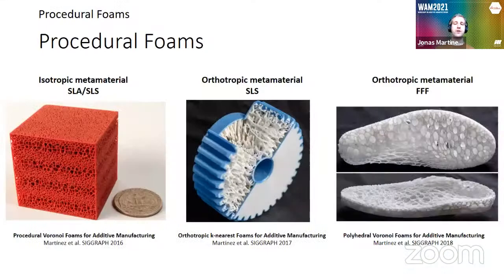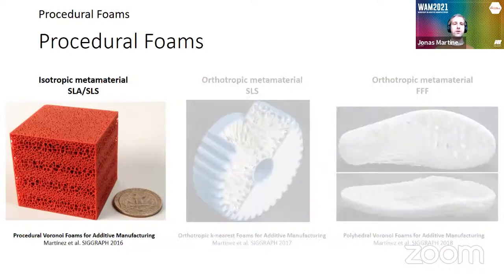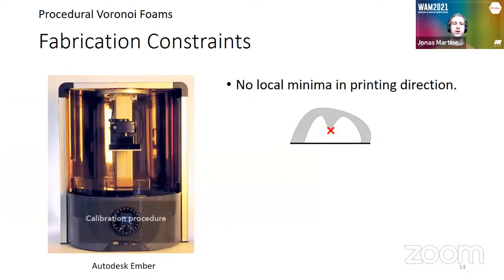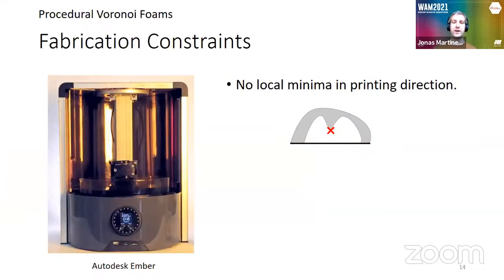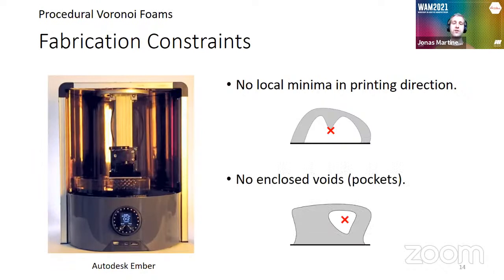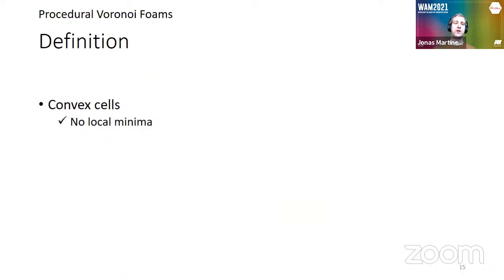And we have three representative examples to show. The first one is targeted to SLA and SLS. And here, I'm going to play the video again. We had the following fabrication constraints. Basically, you cannot have local minima when you print, otherwise it will not be properly attached. And in this kind of technology you cannot have enclosed voids, because they will trap the resin inside. So we thought that a structure with convex cells would be nice, because then we can ensure that we have no local minima. And if these are open cells, we have no enclosed voids.